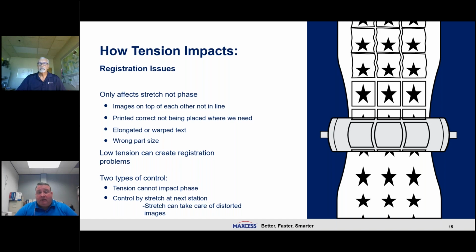What you'll find when we're talking about the changing materials, the thinner materials, is that a machine that may have been working the last 20 years just fine, I'm picturing at the moment printing with die cutting at the end. I'm also picturing maybe a lamination that happens to the top of the web after the print before the cut. This machine may have worked fine for 20 years, and now all of a sudden you're starting to see some issues at the die cut, let's say. And that can be because what used to be 40-pound weight paper is now 15-pound weight, or their films, as Cris was saying, that are getting thinner and thinner, and they're becoming more stretchy. Those are things that will cause a machine that has been working to need to be looked at again and possibly upgraded in some cases. And that's kind of what we're going to talk about here. Those thinner webs, those stretchy, really what we're talking about is stretch in the material before the die cut. That's what we need to prevent.